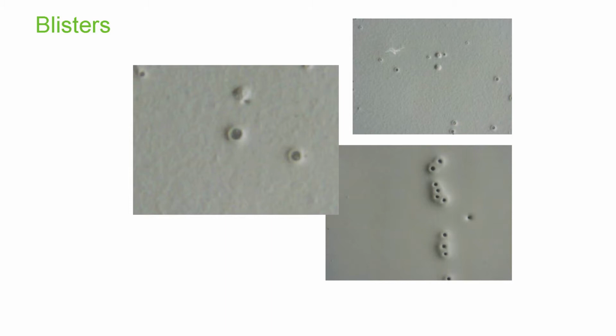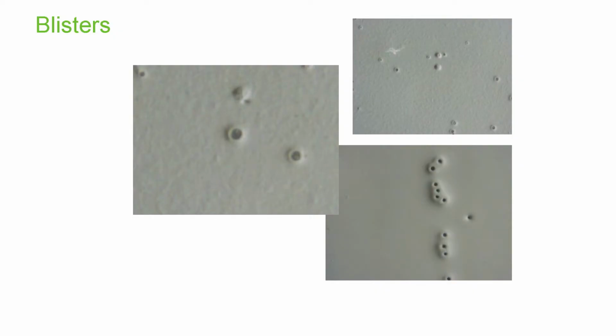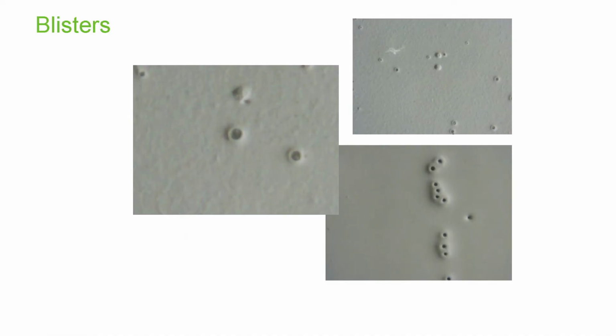You've got to somehow get the majority of that solvent out before the film becomes cured enough that when the solvent begins to blow out, it won't form this volcano. From a chemistry standpoint, we do that by modifying the crosslinker that we're using, the acid catalyst. We might block the acid catalyst. There's a host of solvents that we would choose. So these problems, thankfully, are not common, because what happens in a thin film like this, maybe it's 15 microns, maybe it's 20 microns, this is not a usual event.